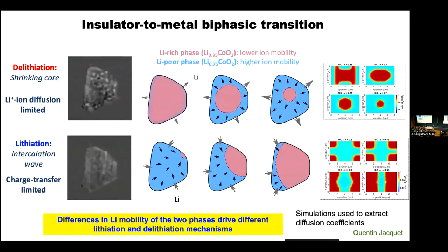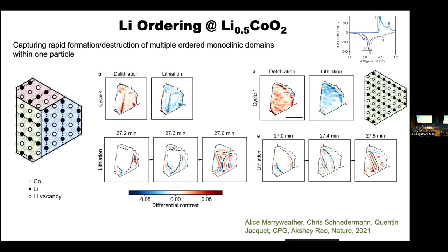So if you just do a thought experiment, the pink particles have very poor lithium mobility. You pull the lithiums out on the edge, and you form this blue phase. And then it's easier to keep on pulling the lithiums out from the blue phase, and you get a shrinking core. On the way back, you nucleate the pink phase with poor lithium permeability. The lithium can't get through that phase, so they come in through the edges of the particle, they add to this phase, and it moves across. And so this is a balance between how fast the lithium ions go in, which is J, and then also the transport in the blue phases. And you can extract the diffusion coefficients through this. Okay, so that's lithium cobalt oxide.